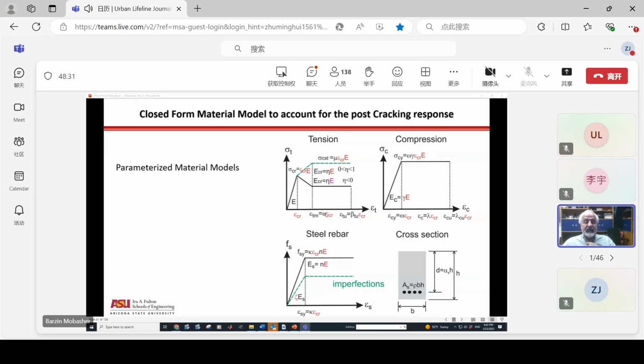So to do that, we need to develop the stress distribution or stress strain diagram as a function of multilinear segments. Why is it multilinear segments? Because integrating a straight line is really easy, and that's what I want to do. But what I also want to do is to use the minimum number of variables. And by minimum number of variables, I want to define two intrinsic properties. One of them is the cracking strain, and the other one is the elastic modulus. So the product of these two gives me your cracking strength, and everything else after that should be a function of it.